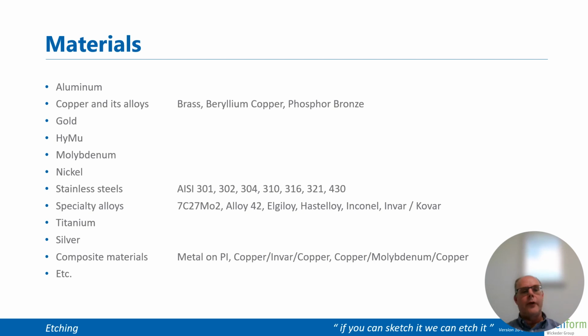I mentioned that you can virtually etch any material. Examples are aluminium, copper and copper alloys, like beryllium copper. Beryllium, if particles are airborne, can be very dangerous to health. And the big advantage of etching is that you dissolve the beryllium so it doesn't get airborne. You can etch gold, molybdenum, of course all stainless steels, titanium, but also composite materials like metal on a polyimide carrier or metal sandwiches like copper-invar-copper.